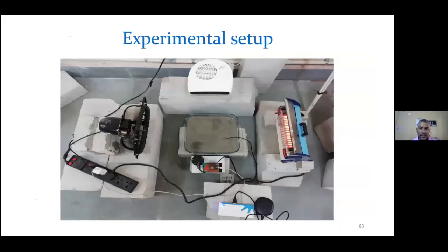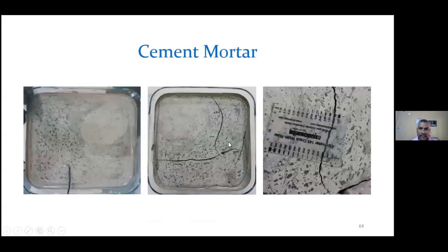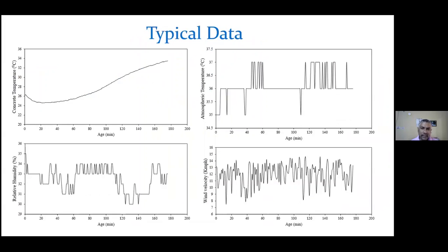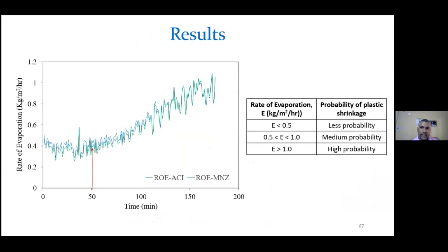But in the laboratory, varying atmospheric temperature, wind velocity, and relative humidity is a difficult job. So my students have tried a temporary setup where we can vary temperature, wind velocity, and relative humidity, everything, and check. And we found the plastic shrinkage crack to form by forcing different parameters. And these are some of the data that we have got in our cloud platform. If we can get this type of information, that the rate of evaporation is exceeding a particular value, 0.5 here, then somebody has to cure the structure to stop this plastic shrinkage crack, right? If this crack happens, then the long-term behavior of the structure will be compromised.